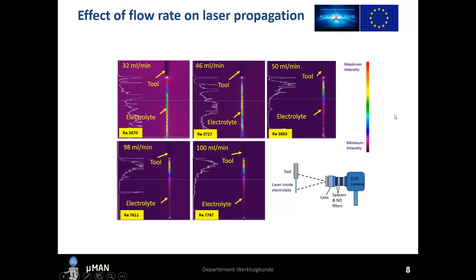The laser power is not only determined by our tool, and not only by what we give into a controller. It's also a function of the flow rate we use for the electrolyte in our system. It's a compromise between what flow rates are good for flushing for the ECM process, as well as for the alignment of our laser. At low flow rates, up to 32 ml per minute, the laser is perfectly aligned, because the electrolyte is a perfectly cylindrical shape and very transparent, so the laser can propagate over long distances and the alignment is very good.